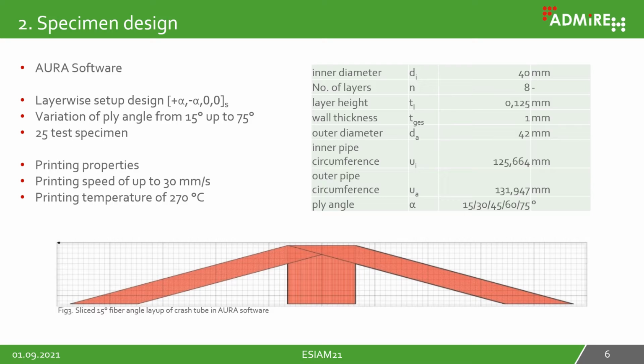On the right side in the table, you can see the inner diameter of the tubes were 40 millimeters. The total number of layers is 8. The layer height is 0.125 millimeters, resulting in a wall thickness of 1 millimeter and an outer diameter of 42 millimeters. The printing properties were based on the material we used from Markforged.